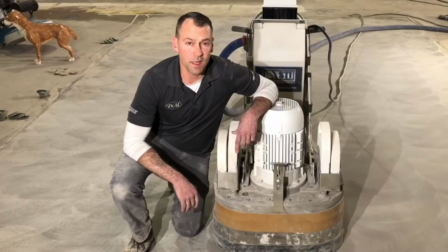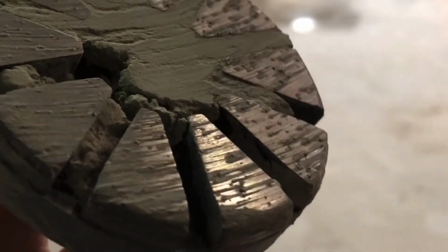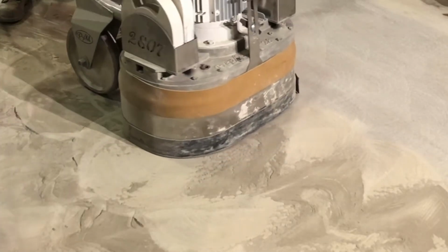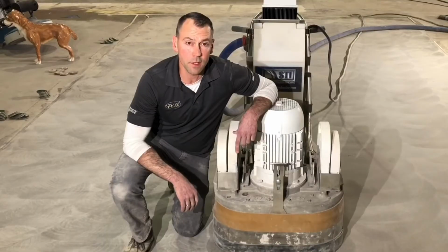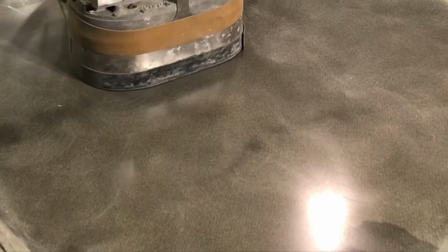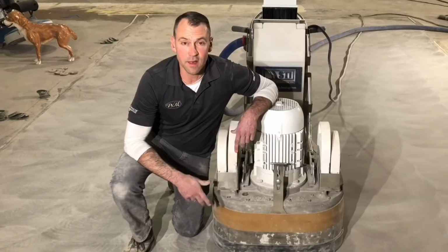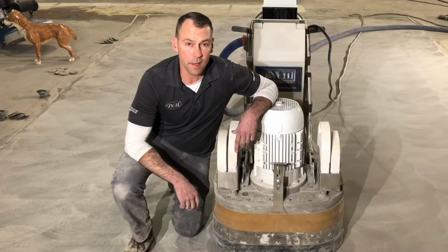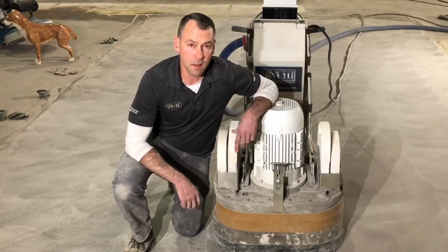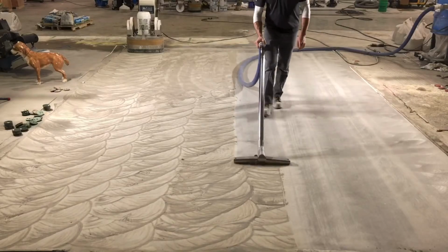So the choice was made to drop to a 16 grit, which is a much more aggressive diamond, and the idea with that, of course, is to remove that bulk material much quicker than a 40 grit could. Anytime we use an aggressive diamond like that, we're concerned that we're damaging the surface to the extent that the next diamond would have to work that much harder to clean it up. There really wasn't much choice. Labor is going to be much higher if we go with, let's say, a 40 grit that's less aggressive or less damaging to the surface, but obviously going to take much longer to remove that much stock.